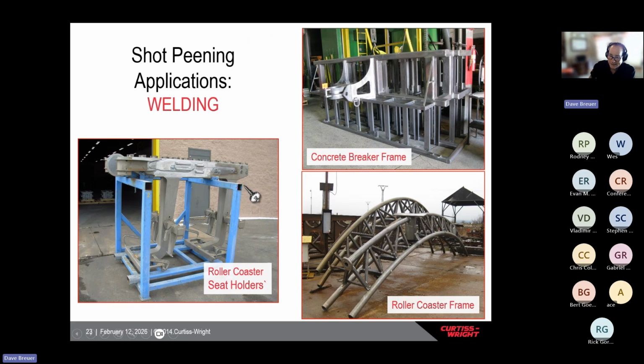But for welds that are in cyclic loading, which vibration is a common one, this frame here has these metal rams that go up and down. This cage gets mounted on the back of a truck, and this is used to break up concrete roads. These metal rams go up and down and break up the concrete so they can sweep it away. There's over 100 spot welds on this frame, and whenever one of these welds would fail, it would shut down a road crew. Since they started shot peening these welds, they've reduced their downtime by about 95%.